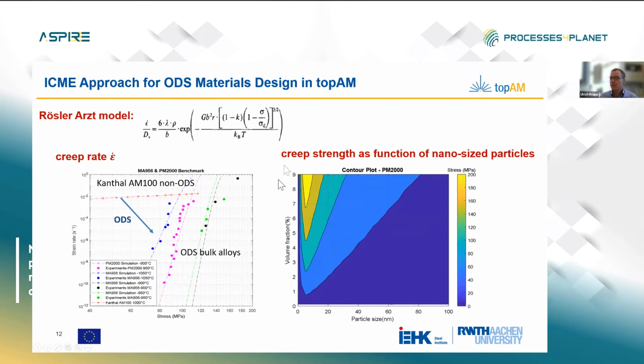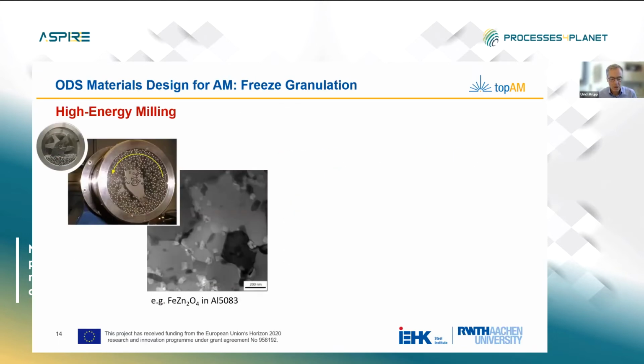And so we are able to use computational thermodynamics, and we get the volume fraction and the particle size. Here we see an optimum that is somewhat below 10 nanometers. That means we really need to have very small particles. Well, so we are using three ways in order to get the small